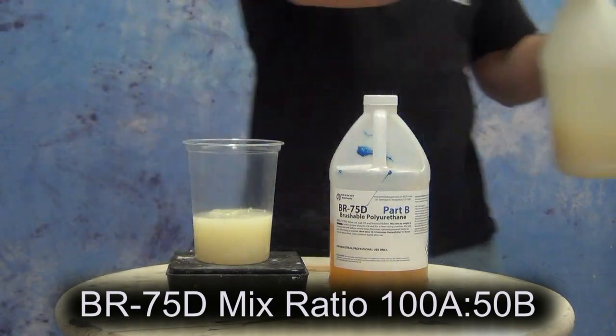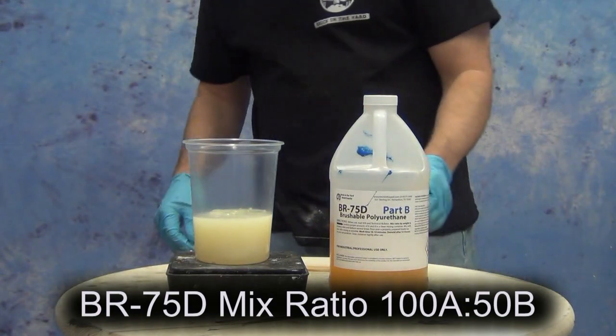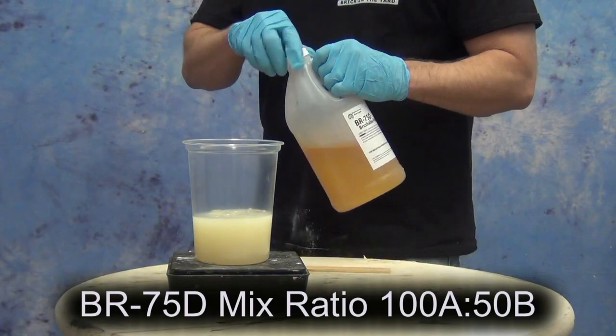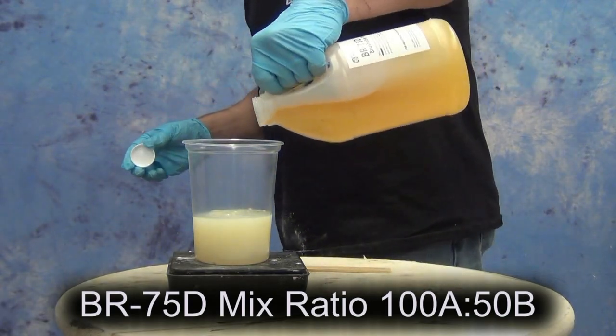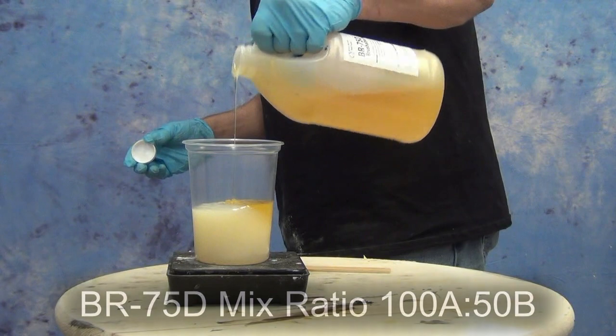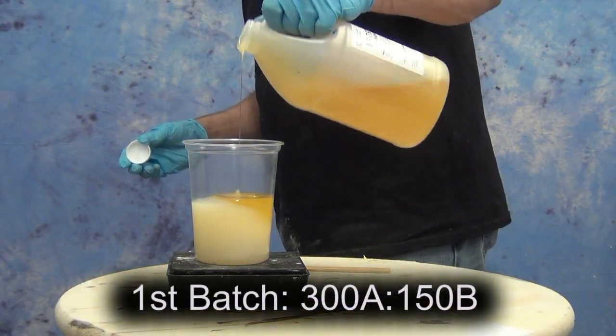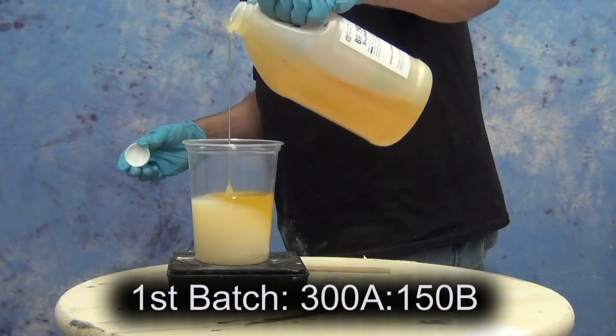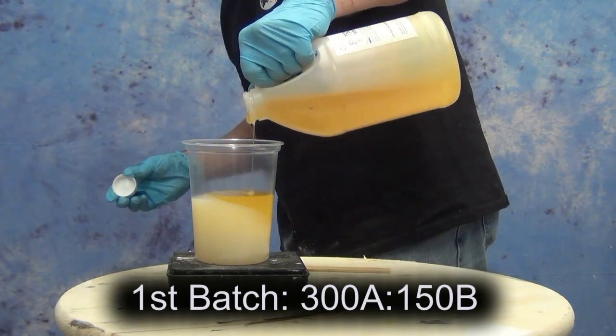And if you do it very carefully, you can get very nice bubble-free casts by brushing this into a silicone mold. Now, the BR-75D has a very simple mix ratio of 100A to 50B, or basically 2 to 1. So in this case, for our first batch that we're applying here, we're going to mix up 300 grams of part A with 150 grams of part B.